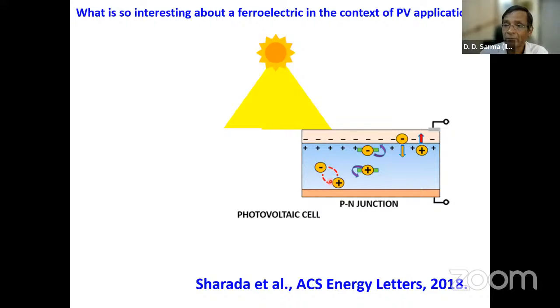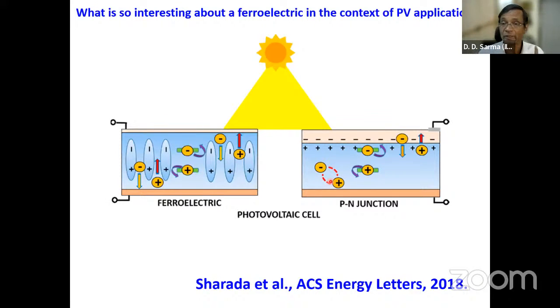They can recombine, and so the efficiency will go down. But if you have a ferroelectric material, it has a polarization throughout the material. So as soon as an electron and hole are generated, it doesn't matter where, locally, all the electrons will go to the positive end of the ferroelectric domain, and the hole will go to the negative end.